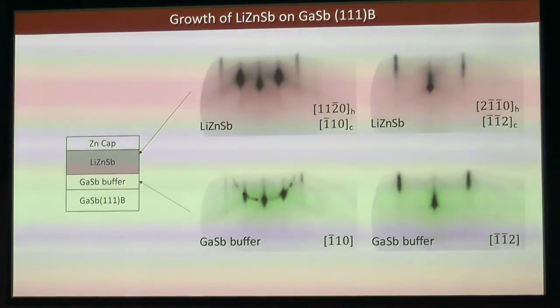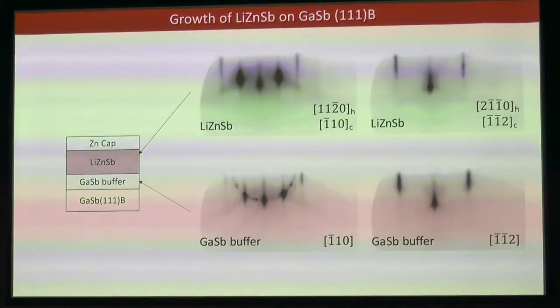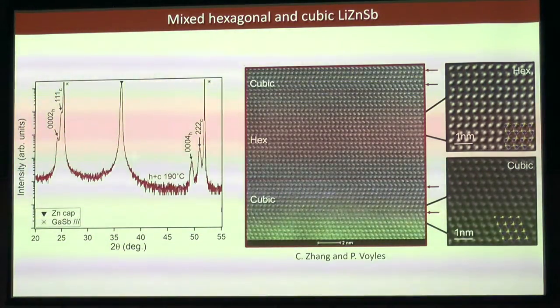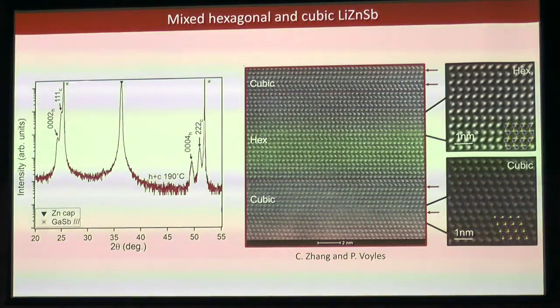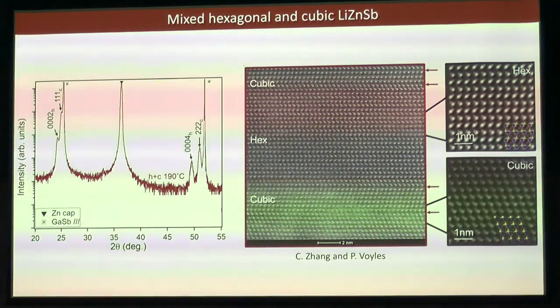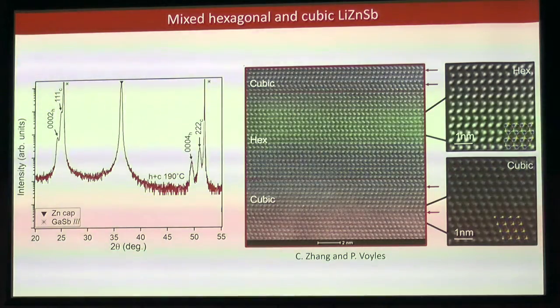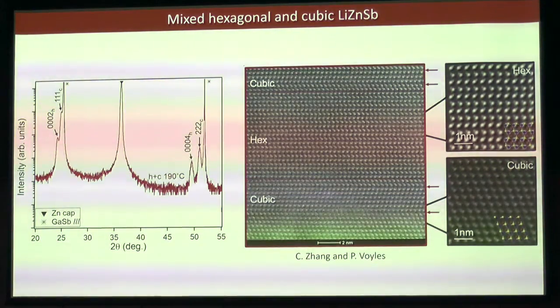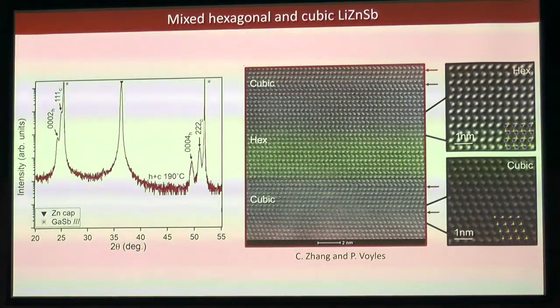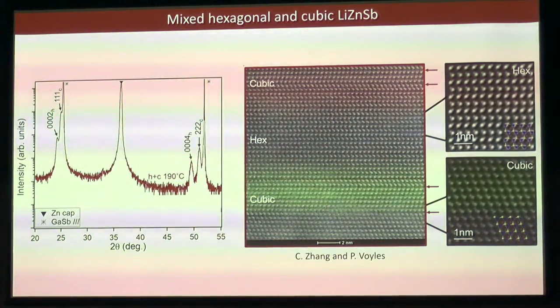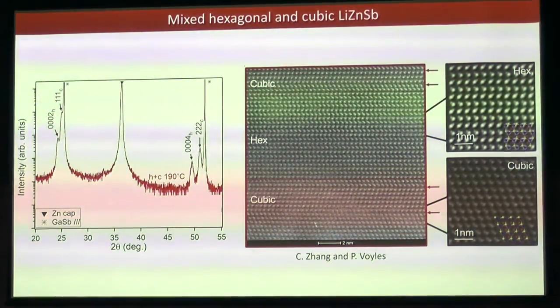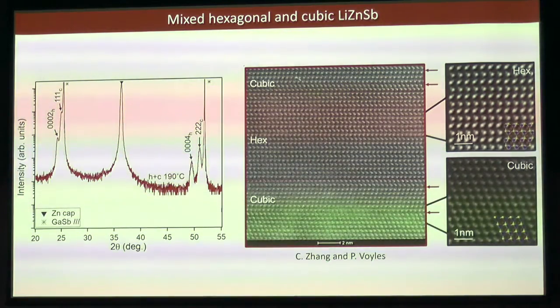Okay? If you take this sample, which looks beautiful in the RHEED, and do X-ray diffraction, here's what you get. These very sharp reflections: this is a substrate reflection, this is a substrate reflection, this is the cap of zinc that we put on top. In addition, we see two sets of reflections that correspond to the film. If you look a little more carefully, this one corresponds to a hexagonal phase, and this one corresponds to a cubic phase. We can confirm that by cross-sectional TEM from our collaborators. This whole field of view is the film, lithium zinc antimony. We have cubic regions with ABC stacking, hexagonal regions with AB stacking, and cubic regions.